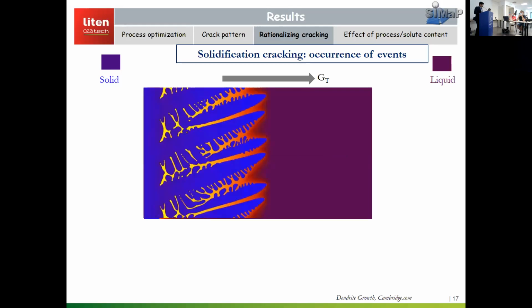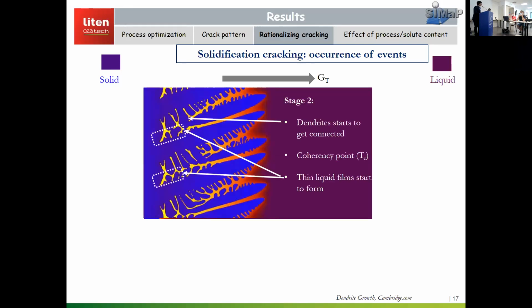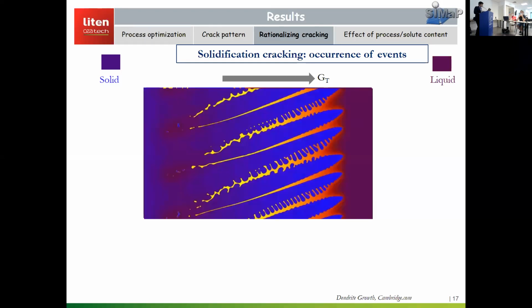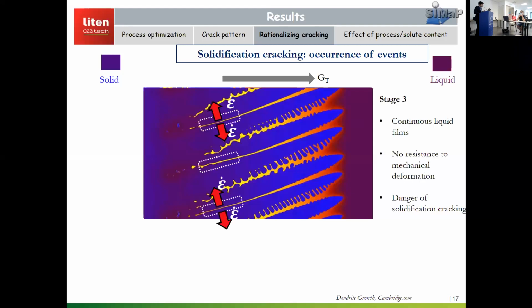So if you continue the solidification, you reach a particular stage where dendrites start to get connected to each other. And this is a point where we can say the coherency point, and where a liquid film starts to form. Now, further continuing the solidification, we can see the third stage where the liquid films are continuous in nature. And since they are continuous, the mechanical resistance of these liquid films is very low. So this is the most sensitive region of the dendrite morphology where solidification cracking can occur.